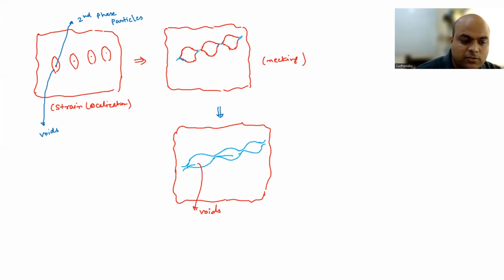And the structure you see, now if you open these parts, there are two parts, right? This is the line where the fracture of the sample is occurring. So now you have two parts. If you see these two parts from the top view, you are going to see voids, big voids, on both sides of the sample.